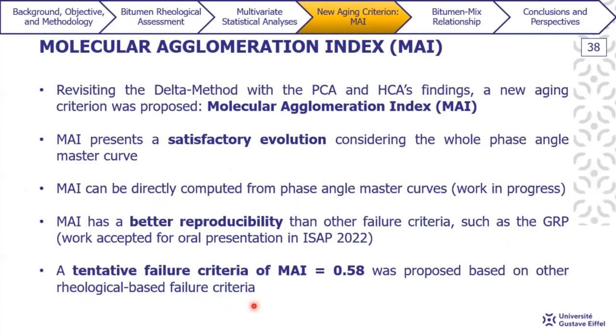So the partial conclusions of this part are that by revisiting the delta method with the PCA and HCA findings, a new aging criterion could be proposed, which is the molecular agglomeration index. MAI presents a satisfactory evolution considering the whole phase angle master curve. MAI can now be directly computed from the phase angle master curve. This work is now in progress. MAI has a better reproducibility than other failure criteria, such as the Glover-Rowe parameter. Again, this work will be presented in the next ISAP conference. And the tentative failure criterion of MAI equal to 0.58 was proposed based on all the other rheological-based failure criteria.